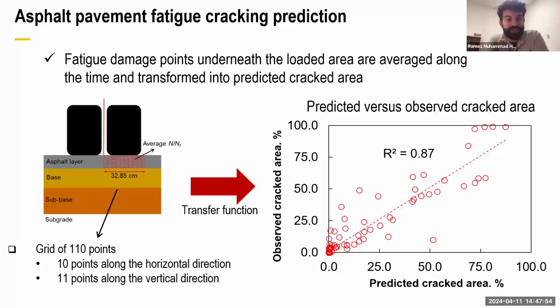My question is about the modulus input for the FlexPAVE model. Usually with these kinds of damage models, especially if you're looking at bottom-up fatigue, the modulus is very critical, because the strain can be much lower if you have a high modulus. Did you conduct any sensitivity analysis looking at the modulus? And I ask this because, for example, if you start to include a lot of RAP, I know you mentioned RAP, usually the modulus will get much higher, and actually you'll have very good bottom-up fatigue cracking by these types of models. So did you conduct any sensitivity analysis for the RAP?